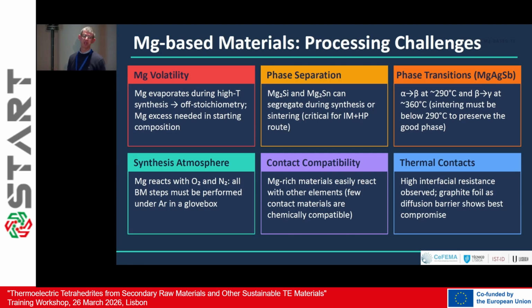So we have the problem of volatility of magnesium. Actually, magnesium is quite reactive, and not only evaporates and sublimates very easily, but also reacts very easily. In case of magnesium silicide, if you come just from melting, you can have phase separation. In case of magnesium silver antimonide, you have this problem of several phase transitions depending on the temperature. And of course, magnesium, as I said, reacts very much with everything, in particular with oxygen. So it's necessary to make the synthesis in an inert atmosphere, in particular if you use ball milling.